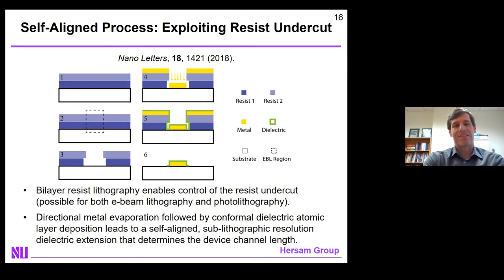And so if we fast forward to 2018, let me introduce one of the key innovations in the processing that's going to allow us to achieve a higher degree of functionality. And this is not really a new concept, but it's perhaps used in a new way. And that is the idea of achieving undercuts in your resist profile. This can be done in many ways. One of the simplest ways to explain is a bilayer resist. And when you expose the bilayer resist, assuming that the lower resist develops more quickly than the top resist, then you'll get an undercutting laterally, which creates the profile shown in step 3.